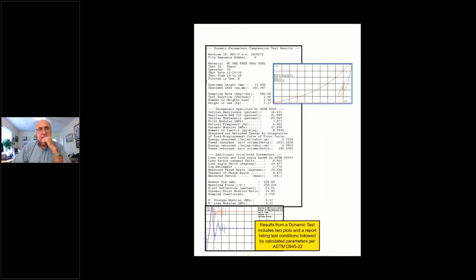Now, the next slide shows us the output that we generate from a test. The first thing I would like to refer to is the load versus displacement plot up on the right top corner. This specimen gives us quite an angle, quite an area under the plot, which shows that loss energy is substantial. As we go down to energy resilience, in this case, 16% definitely shows that it is not an elastic product, but more of a damping characteristics. The energy hysteresis is 83%. That is quite high, so loss energy is very high.